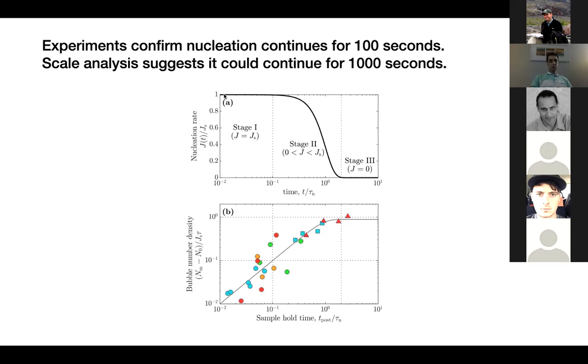Here I'm showing nucleation rate scaled during samples' annealing time. Nucleation rate can be divided into three stages depending on the ratio of time over nucleation time scale. At first, up to 1/10 of the nucleation time scale, nucleation rate is at its maximum. After that, it starts decreasing with time, and then it reaches zero, where samples are at equilibrium at this stage.